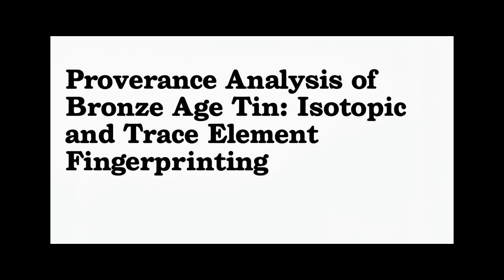And the science itself is always evolving. Researchers are even conducting smelting experiments to understand if the process of melting down ore and extracting tin might slightly change its chemical fingerprint. This is called fractionation, and accounting for it is crucial for pinpointing origins accurately. Of course, it's not all straightforward. There are still challenges. Sometimes, the chemical signatures of different ore deposits can look quite similar, making it tricky to be 100% certain. Plus, we don't yet have a complete global database of every single potential Bronze Age tin source.